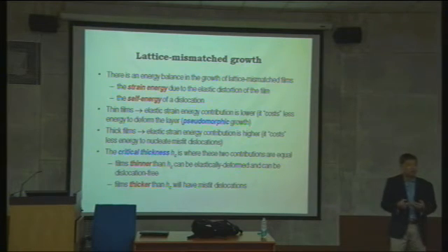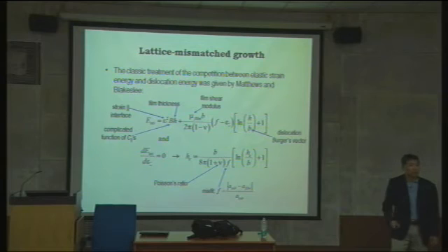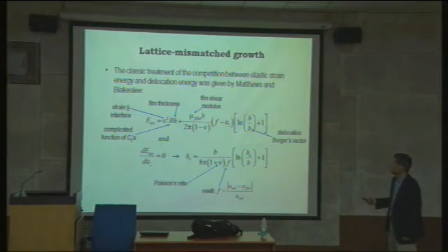So how do you predict this critical thickness? Critical thickness has actually been studied in semiconductors in great detail. The equation looks complicated, but it is an energy calculation, a thermodynamic calculation. There are a lot of terms here: the Burgers vector of the dislocation, the film shear modulus, and the film thickness h, and then this b is a complicated function of the compliance and the interfacial strain. You have a lot of terms, but I think we have to consider Poisson's ratio and misfit.